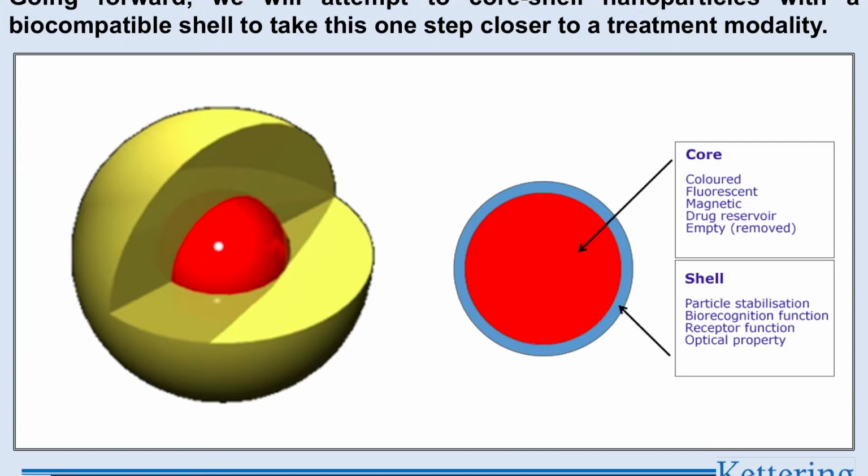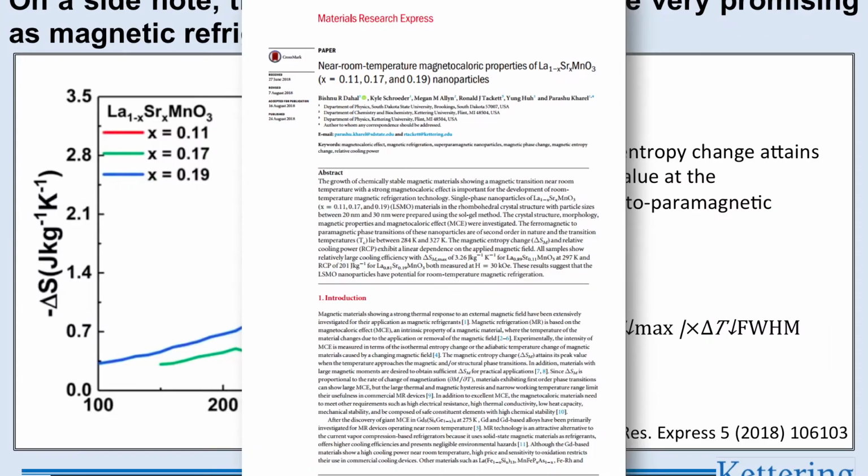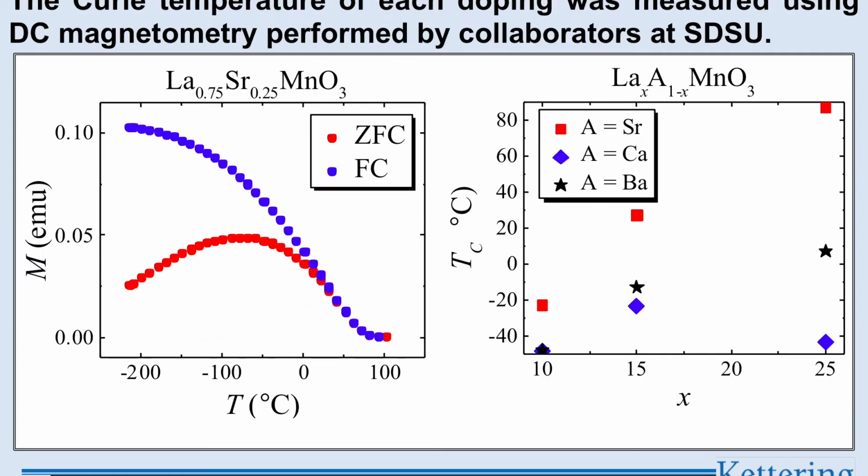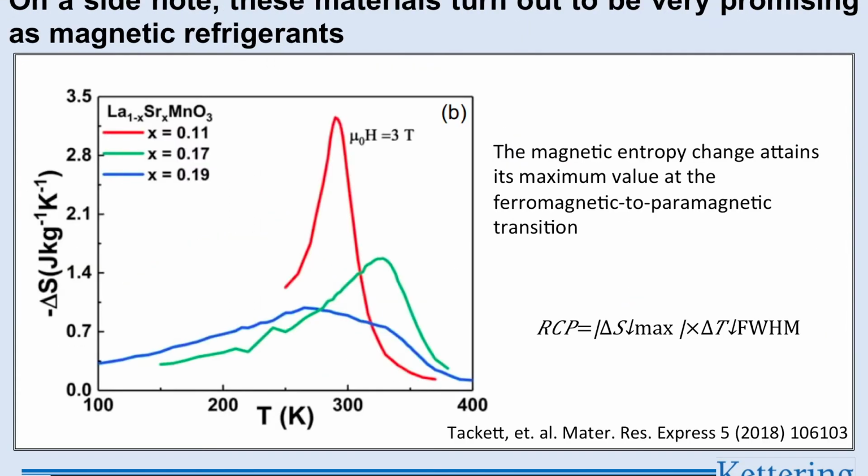What we'll probably try to coat it with is silicon dioxide, SiO2, essentially sand, which is relatively biocompatible. The whole idea is to isolate those heavy metal ions from leaching into the body, coating them with something that will hold them in there but not affect the magnetic response much. So that's what we're currently working on. And ultimately they're excreted, you're saying? Yep, that would be the hope.